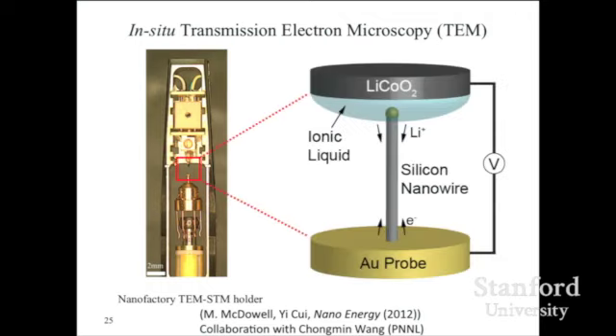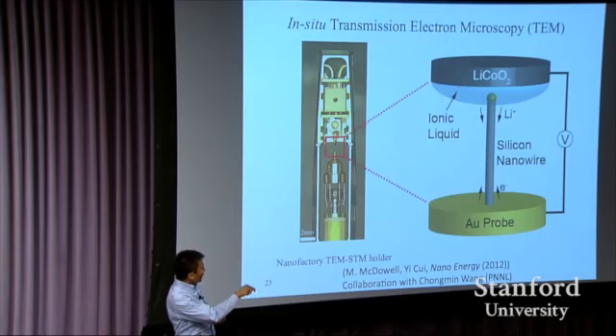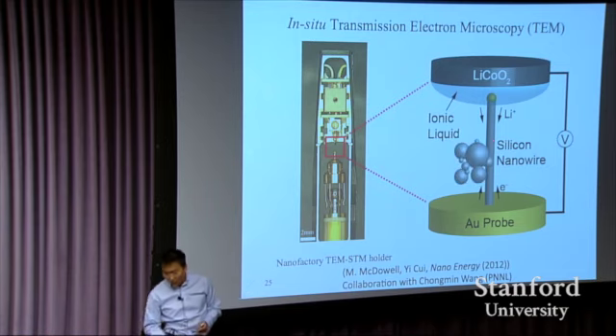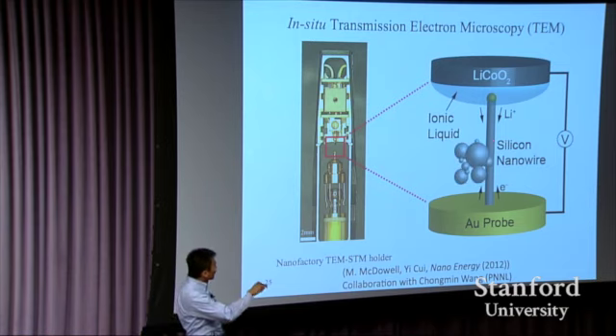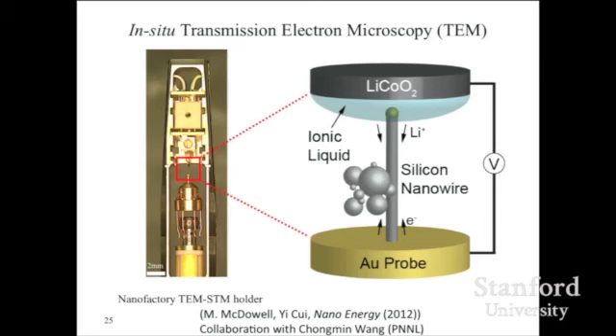So you can mount, for example, a nanowire onto a metallic contact, having the positive electrode right there, insert this nanowire into ionic liquid, charge up your battery, electron comes in, lithium comes in, you can see them react. You can also put the particle in, electrons can jump into this particle, lithium can also jump in, also charge up your battery to see what happens.